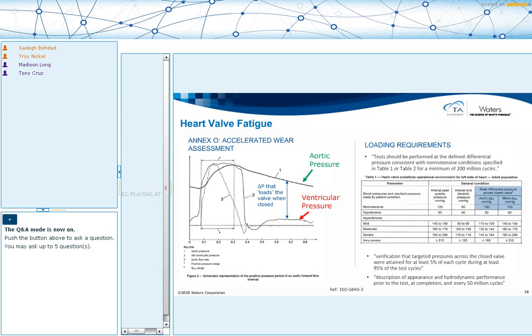There are three things that you are going to look at. You are going to make sure that that pressure differential is achieved. So your pressure differential should go above 100 or 120, and it is maintained for 5% of the time of each cycle. And you have to make sure that that happens for at least 95% of your test cycles.